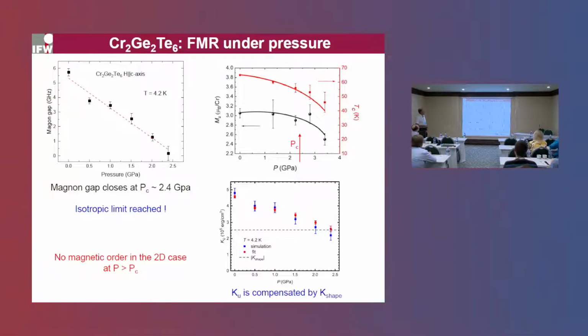For that, we made static magnetization measurements under pressure, and we found that up to the critical pressure for the closing of the gap of 2.4 gigapascal, the ferromagnetic order is still present in the bulk limit, and the magnetization doesn't change substantially. So that means we reach the isotropic limit by changing the intrinsic magnetocrystalline anisotropy so that it's fully compensated by the shape anisotropy, which is always in plane.